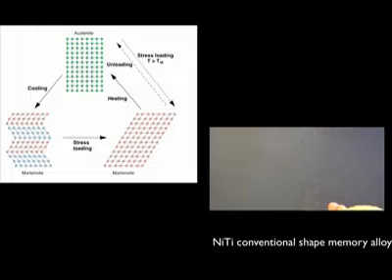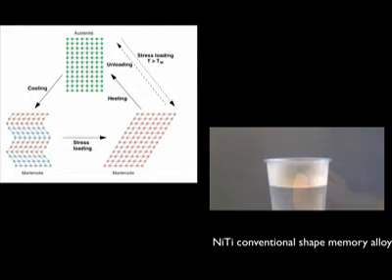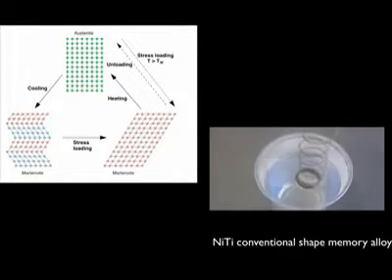Beginning in the lower temperature martensitic phase, the twin variants are realigned through the application of stress as the material is deformed. Heating the sample back up so that it re-enters the higher temperature austenitic phase restores the material to its original shape.